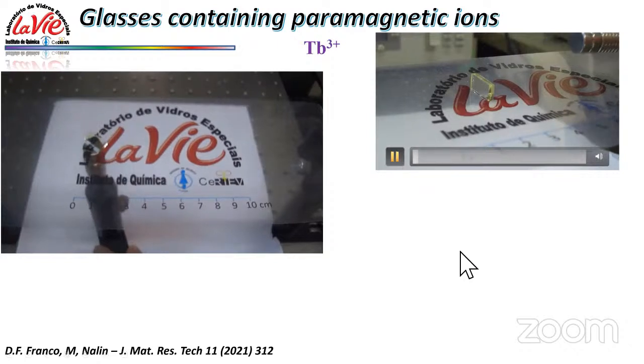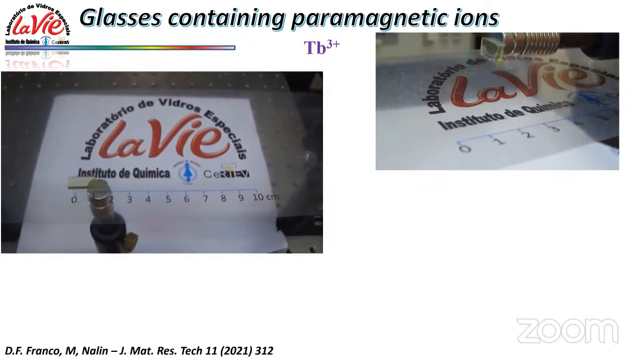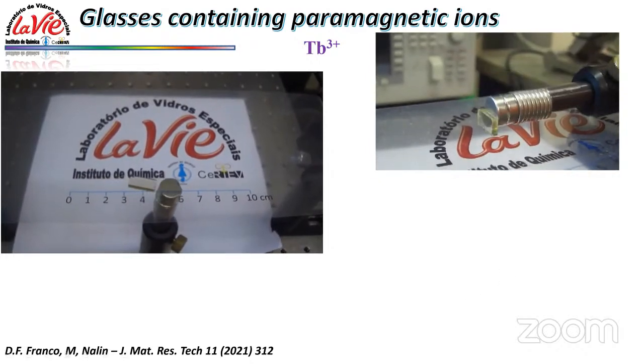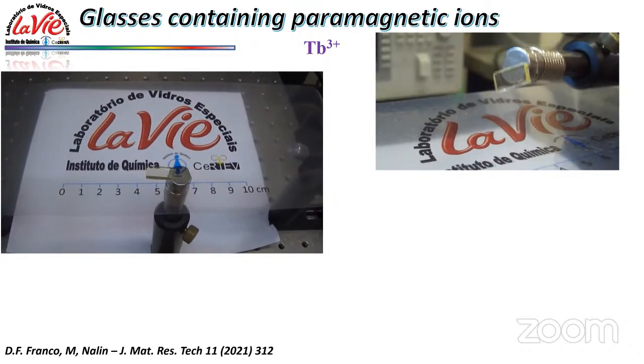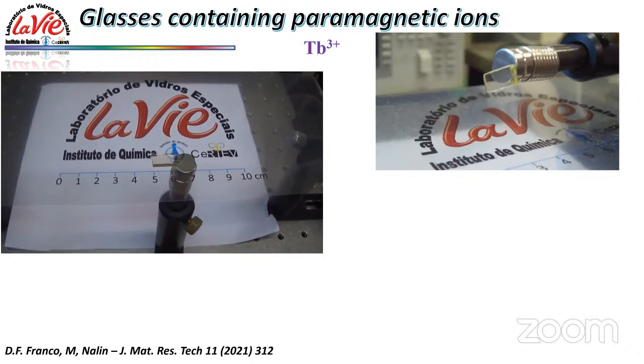So we just have here some images and some videos about this glass. These are borogermanate glasses, so we can put a high content of terbium in this composition. Of course, we need to manage it, because terbium at high temperature and high concentration can change its oxidation state, passing from terbium 3+ to terbium 4+. And in this case, the glass becomes dark, so we lose the optical properties. But by working on the chemical composition again and putting in the correct agent to control this redox problem, we can get very high concentrations of terbium without oxidation.